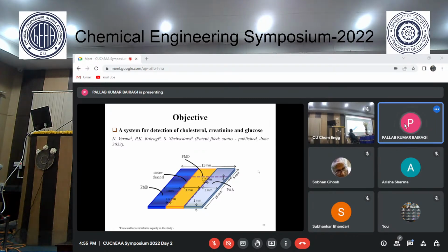The three parts are then further used for developing different electropolymers over them: polymethylene blue, polymethyl orange, and polyacrylamide separately on each segment. During the electropolymerization, the other parts were properly covered so that we can avoid the overlapping of one electropolymer onto the others.